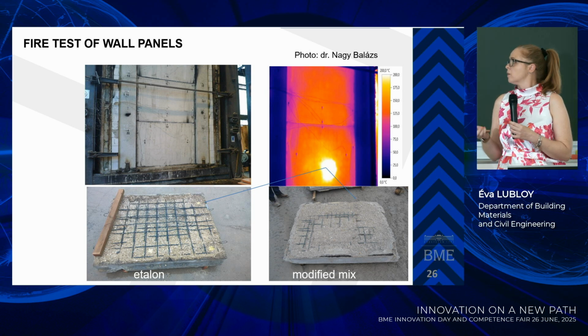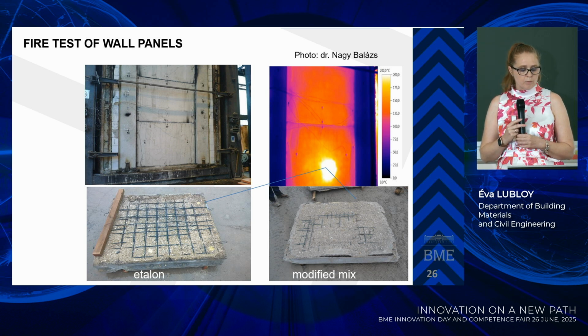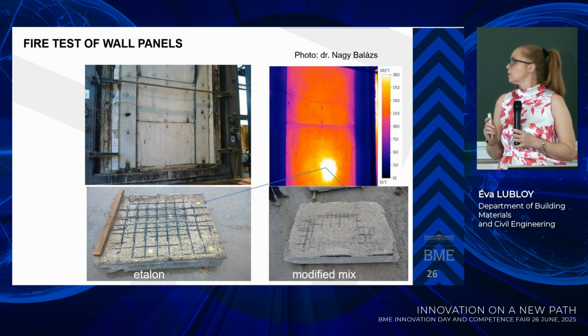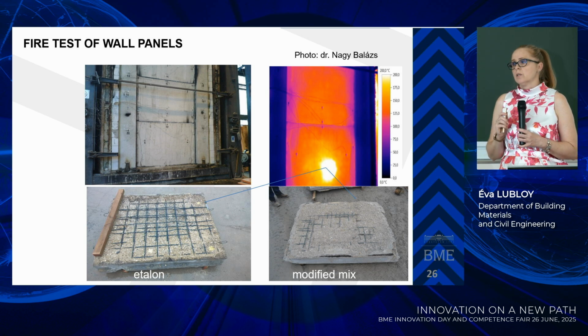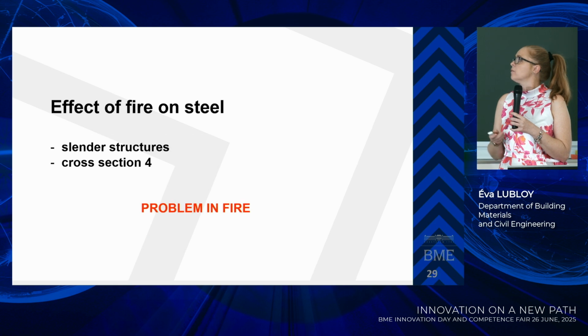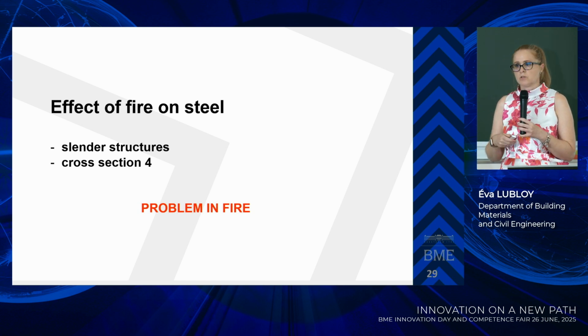Yeah, what happened with the elements? In the first mix, we have spalling of the concrete core. I think it is to see that the reinforcement deformed. In the second, after changing the concrete composition, we have a smaller amount of spalling of the concrete core. Yeah. What happens if we have steel structures? In case of steel structures, the direction is that we always use smaller cross sections. If we use slender structures, smaller cross sections, then we have problems. We have other statical problems, for example buckling, and we should make the measurements differently. And a thin cross section could heat relatively rapidly, and we have problems.